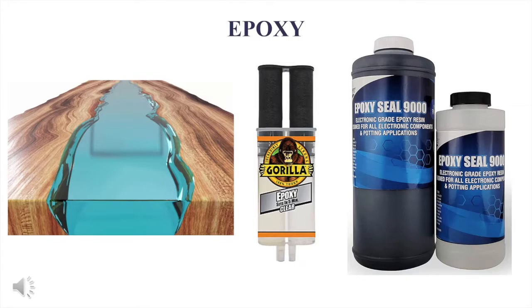The problem with using epoxy potting for the water filter is that the curing reaction is very exothermic, and as a result, heat builds up within the reactor. This heat is transferred to the glass fibers, causing them to break due to an accumulation of thermal stress.